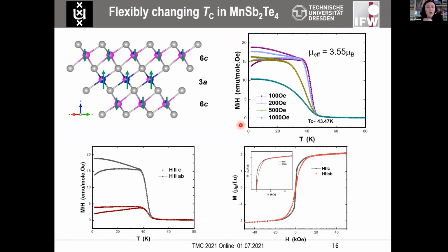So let me show the results we get on the single crystals with the highest TC. So this is at about 44, 45 Kelvin dependent on the sample. So here we have very strong out of plane anisotropy. So it's again an easy axis ferromagnet.